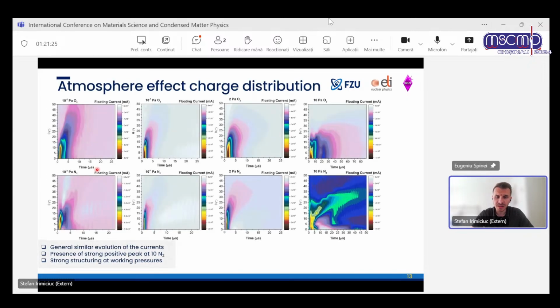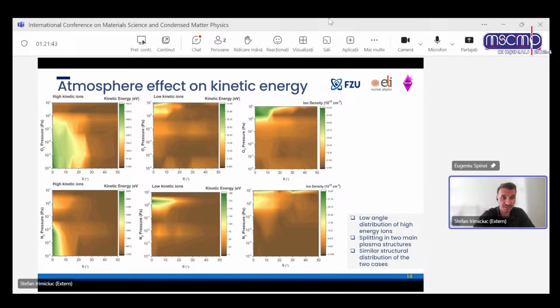And this is basically a little bit of a commercial for our diagnostic tools. We can produce these beautiful maps, which are angle and time resolved. This also tells you where you can put the substrate, and how the position of the substrate will be affected by the energy of the particles, and this is something that you can see here. This is the angle, the pressure, and the kinetic energy of the particle with the ion density as well. So this is for deposition of manganese oxide in different gases.